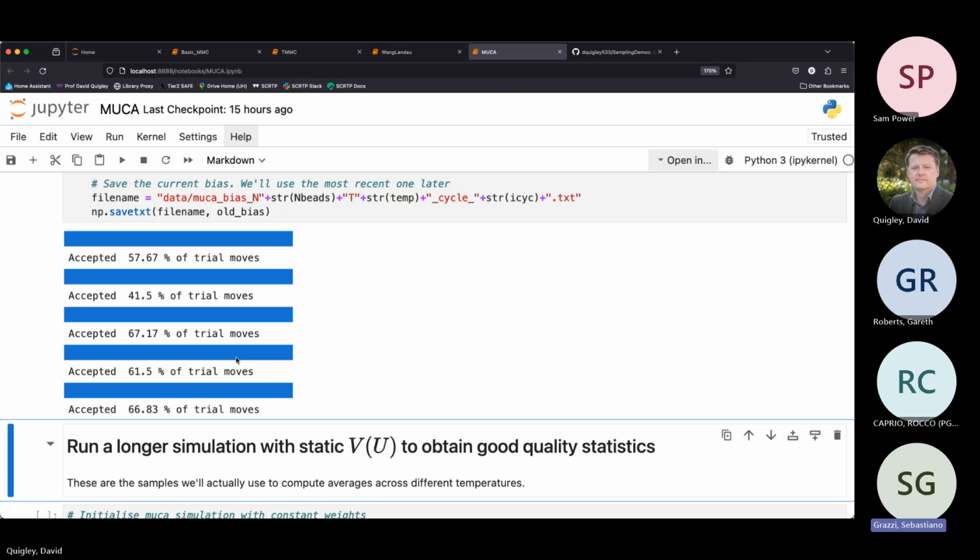So then you're not having to sample all of the mixed phase information in between. You're just going straight from one phase to the other phase. But to make that work, you needed this bias. You need a bias, yeah. And that works really well if you're going between 2 different crystalline configurations, because then you don't have to melt and refreeze to get into the other configuration.